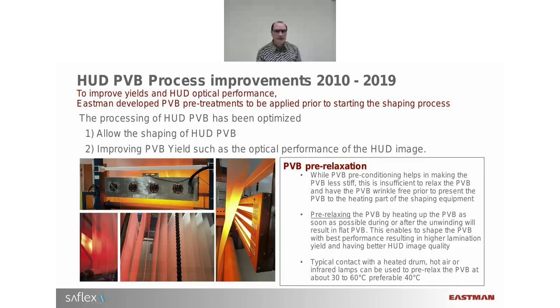The second step, after the PVB is preconditioned, is to perform a pre-relaxation of the PVB. So after the preconditioning, the PVB is a little bit more soft, but still wrinkles are available. You can see them. And if you want to stretch or shape the PVB, it's recommended to have that nicely flat on the heating devices. So to obtain this, pre-relaxation can help a lot.